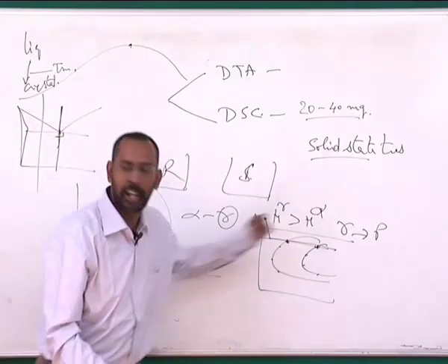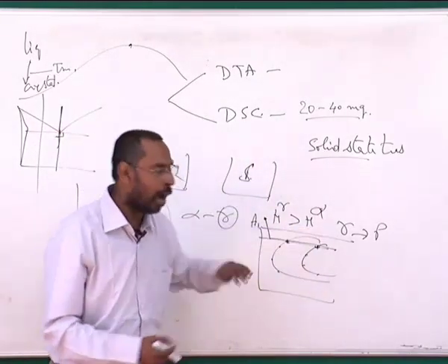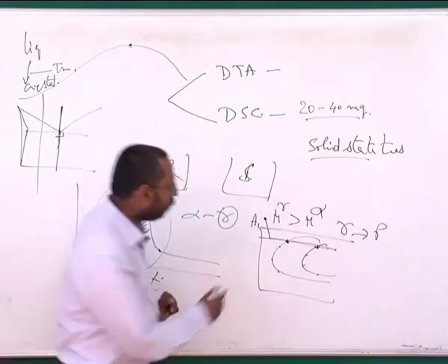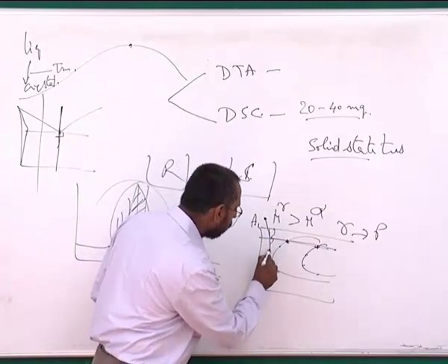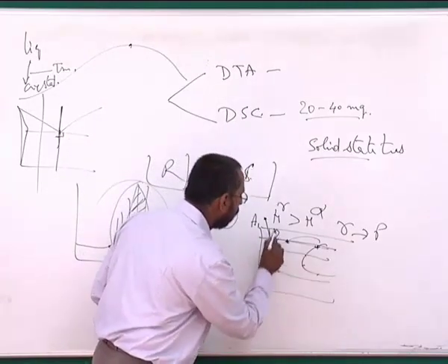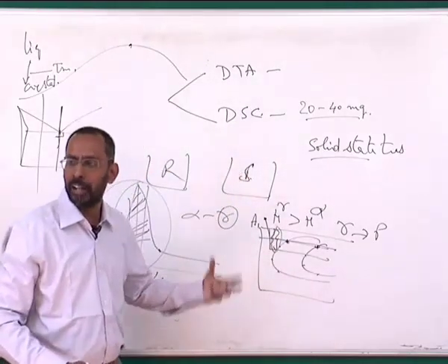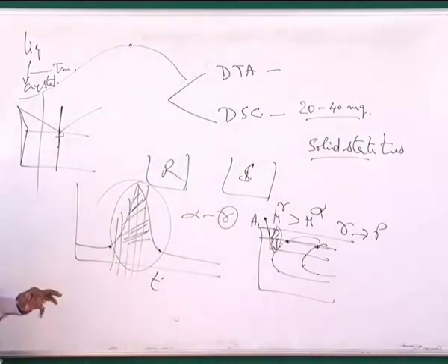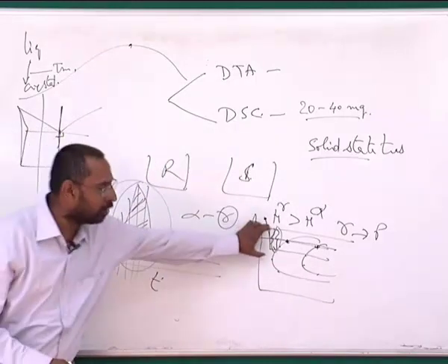So we usually take a large number of samples, hold them, quench them to various temperatures, and what we make sure is that during this transformation, wherever the temperatures I am coming to, nothing has happened. If something has already nucleated, all the kinetics that I am getting are going to be wrong, because some nucleation has already taken place during this.